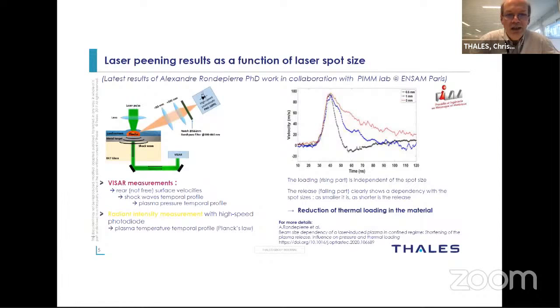The idea was to study the results of laser peening as a function of laser spot size. The setup is that you send a laser pulse on the metal target. You have a confinement layer, which is essentially water, most of the time up to now. You shoot a laser pulse and you generate shock waves. You monitor these shock waves, and in particular the velocity. You can measure the velocity of the shock wave by using a device called VISAR. It's an interferometric device which can deliver the velocity of the shock wave. And we were also recording the radiant intensity with a photodiode.